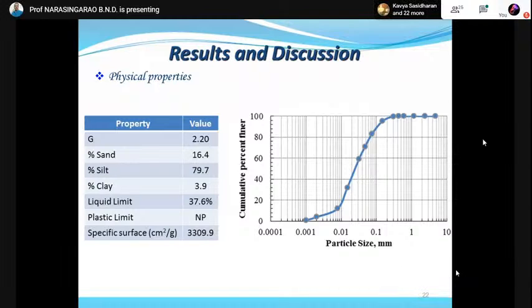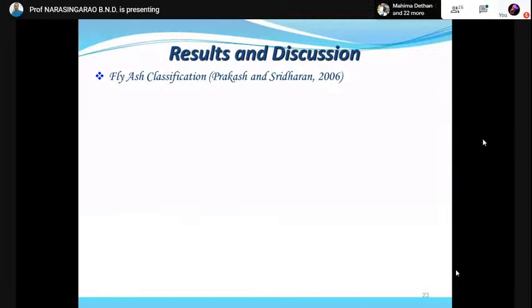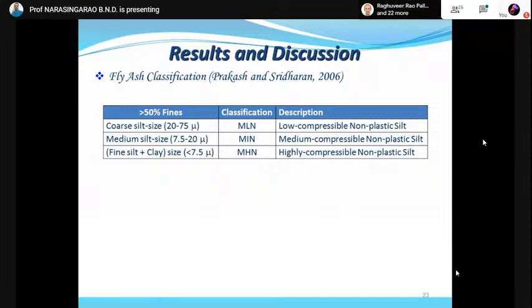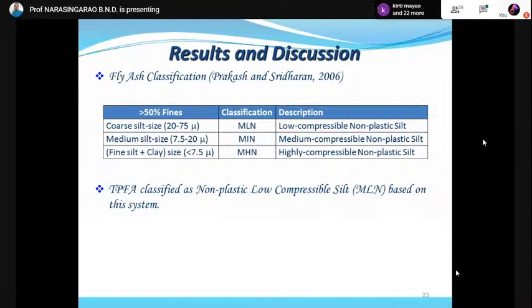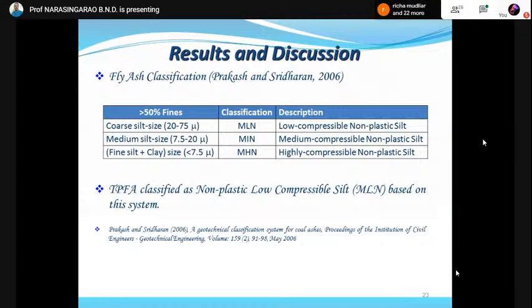So with such a large fine content, it does not fit into the classification system of the ISI, Unified Soil Classification System. Therefore, Prakash and Sridharan have developed a different type of classification for fly ash. If the coarse silt size fraction is more than 50% of the fines, that is of the size 20 to 75 micron, it is classified as low compressible non-plastic silt. And the present fly ash sample comes under this category, classified as non-plastic low compressible silt designated by the symbol MLN.